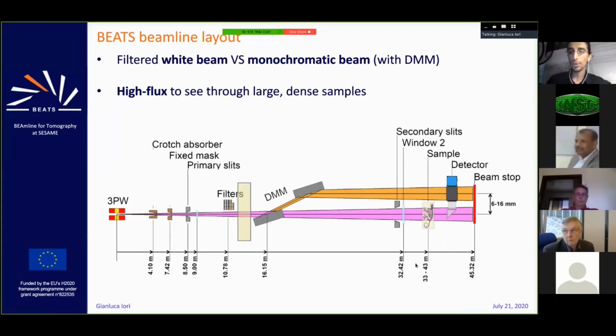So down here at 30 meters, from 30 to 45, we have slits that will tune the size of the beam impinging on the sample. There is a second window, after which we are in air. There is the sample with a manipulator that I'm not showing, and a detector. I will show more in detail what this is. But the message here is that we have already two modalities, a white beam mode versus monochromatic beam mode for selective energies.